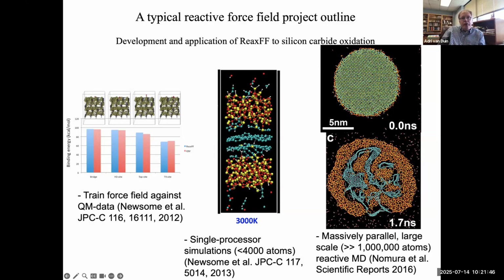Then we start small-scale simulations. These are typically single-processor simulations, smaller than 4,000 atoms, just to make sure that the force field shows the right behavior. So here we start with silicon carbide, we expose it to oxygen, and we see indeed that it phase segregates into silicon oxide and graphite, so that looks good. That indeed is in agreement with experimental observations.